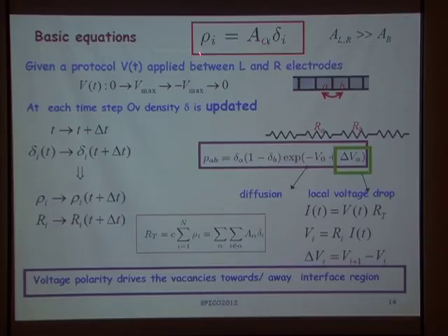So in the very basic linear relation that we have established, which is the most simple one, it's not the only one, of course, we have these parameters A alpha, with alpha being left interface, right interface, or bulk part of the sample, in which we consider in our model that the values of A at the interfaces are larger than at the bulk side of the sample.